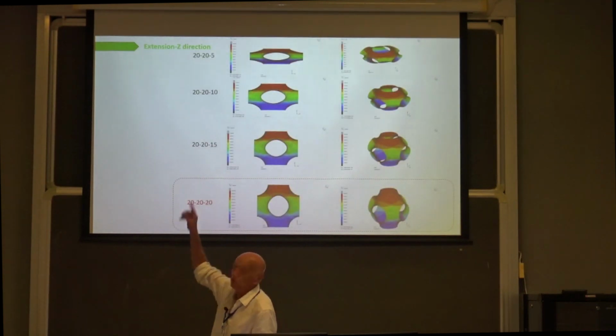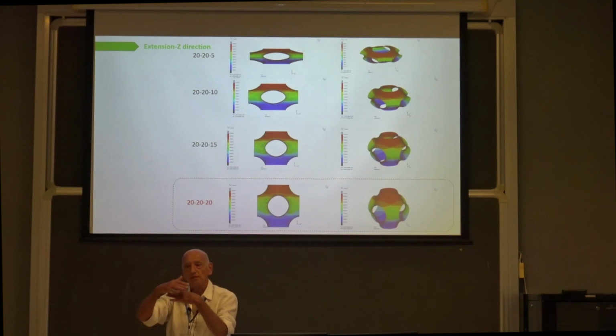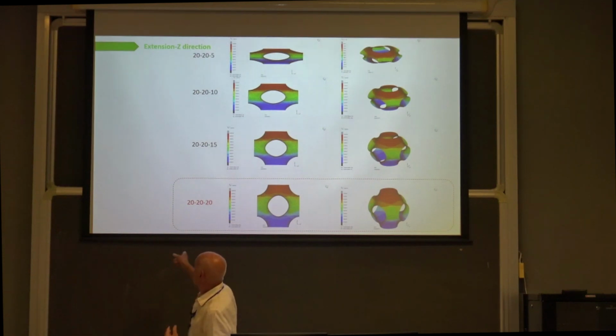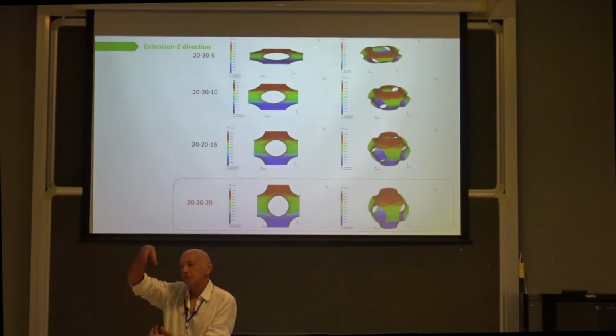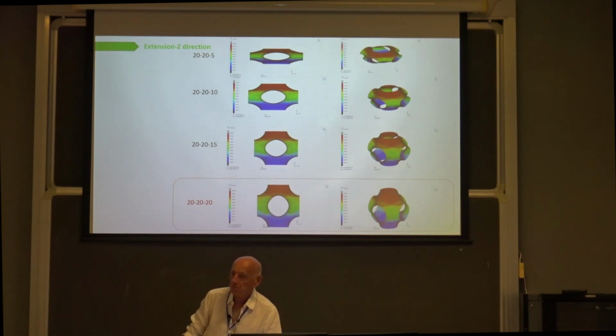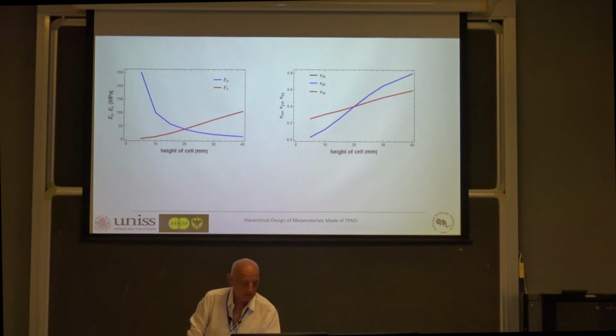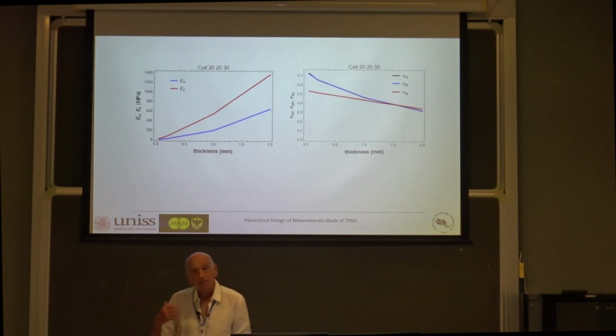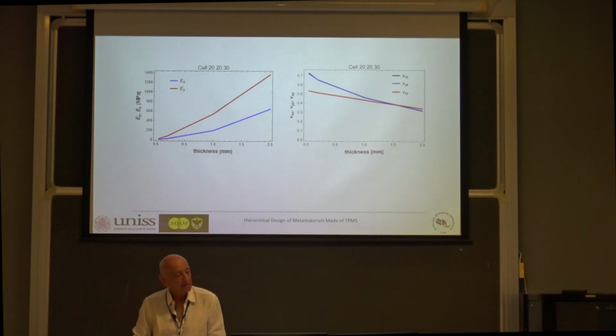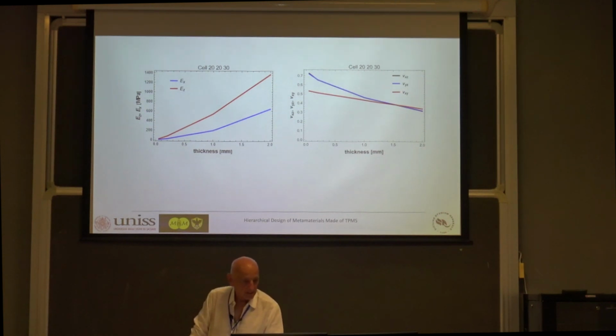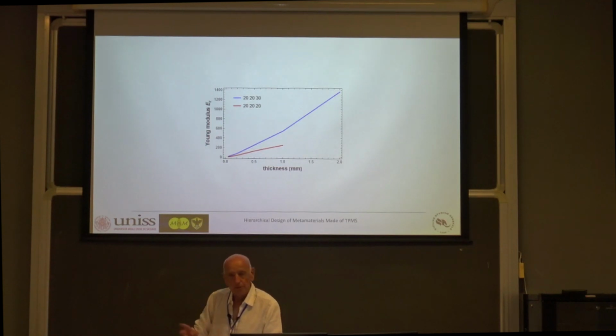If you look at the top, this is a very shallow one. In this case, elongating in one direction is dominated by bending. If you go to the one which is more elongated, it's almost a truss, so it's stiffer. So everything seems to be nice. In these cases, I didn't expect, or at least I didn't hope, that the dependency of the Young modulus on thickness is not linear. So it means that bending now becomes more important, of course. And this is the comparison: the red line is the isotropic cell, and the blue line is the not isotropic cell.